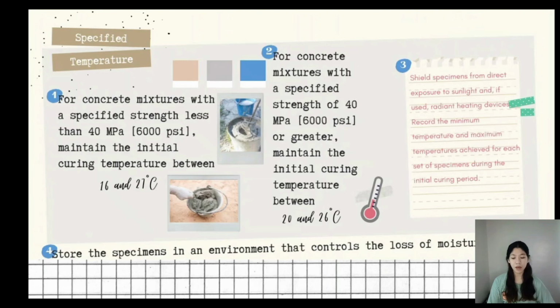Para naman sa mga under specified temperature, para sa mga concrete mixture na may specified strength na less than 40 MPa or 6,000 PSI, kailangan ma-maintain yung initial curing na temperature between 16 and 27 degrees Celsius lang. Kung yung concrete mixture naman ay may specified strength na 40 MPa or 6,000 PSI or mas mataas pa doon, kailangan yung maintained na initial curing temperature natin ay between 20 to 26 degrees Celsius lang. Sinasabi din dito na note, kailangan i-shield natin yung specimen from direct sunlight or direct na paggamit ng radiant heating devices. Hindi naman sa sinasabing bawal, pero kailangan i-avoid natin na direct silang maka-apekto dun sa specimen natin kasi may iba siyang nagagawa.